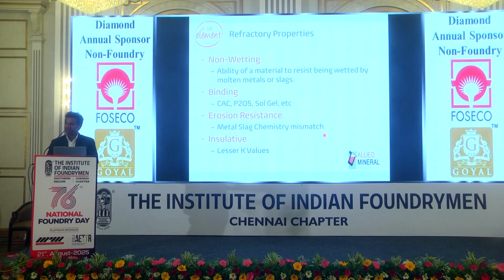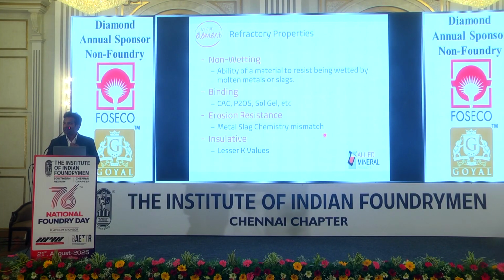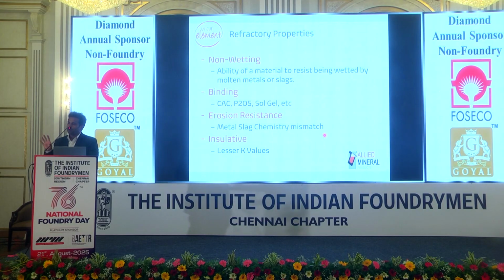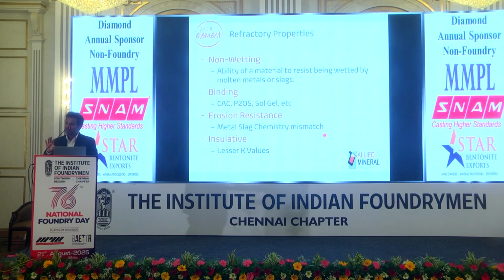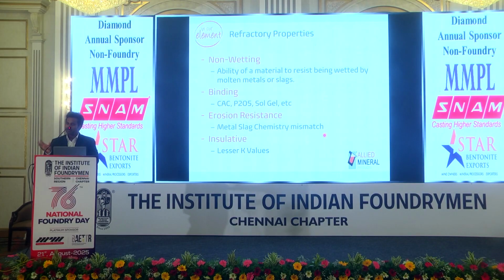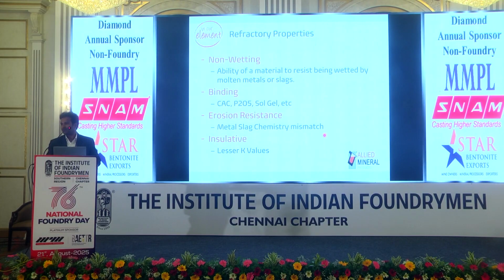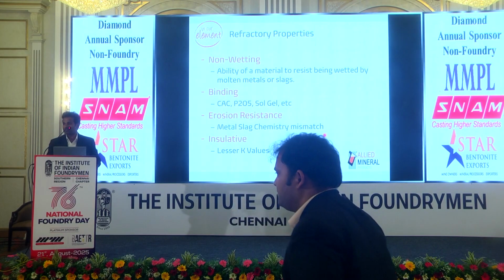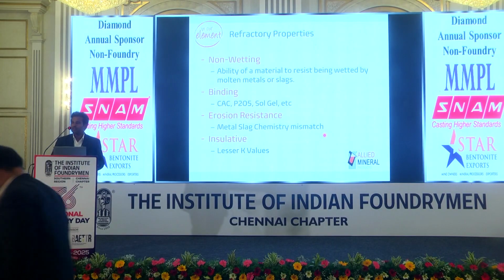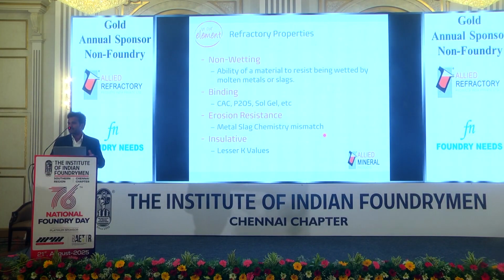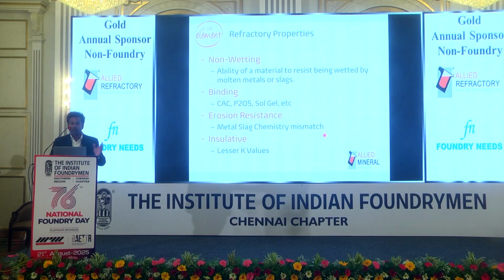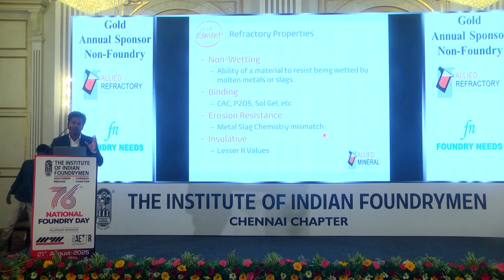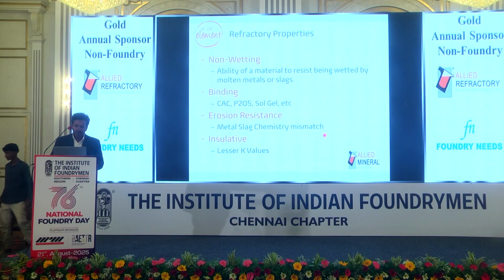Generally speaking, if you have a silicon carbide additive in your refractory, it will have better abrasion resistance and mechanical resistance to erosion. And also you have to use a refractory which is compatible with your metal chemistry. You cannot use a chemistry which is not compatible with your metal and slag, otherwise you will have chemical erosion. And obviously, your refractory should have a very low K value so that your ladle can hold the temperature for a longer period of time.